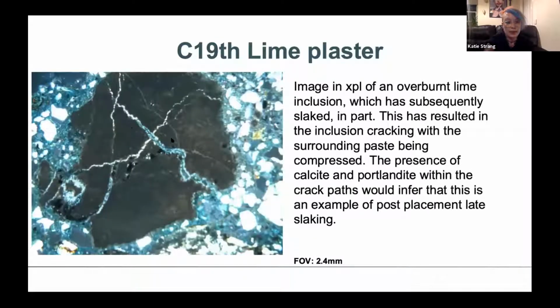This is another overburnt lime inclusion. You can see that really dark colour there. And you can see that because it's been overburnt and it's been in that material, it has subsequently slaked while it's been in situ, which is when you get these cracks form. And you normally know by the kinds of angles that you get between the cracks and the patterns associated with it that has happened because of late slaking of the particle. And you can see in the cracks, there is precipitation of portlandite and calcite, and portlandite is the uncarbonated version of your calcium hydroxide, so the uncarbonated lime that's in there.